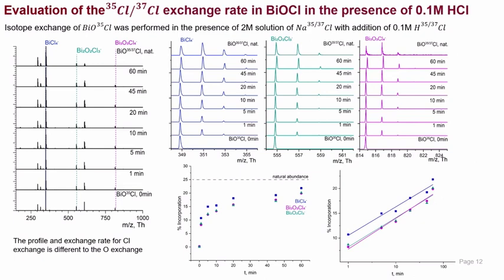And here we also observe incorporation of the isotopes, but the behavior is different. The first step, over the first minute, is steeper, and then we have a slower increase in the second phase of the exchange, rising to around 20% incorporation of the 25% maximum possible for these experiments.